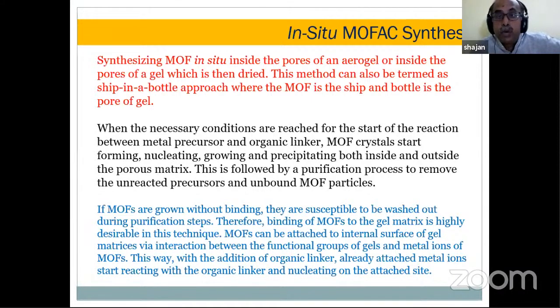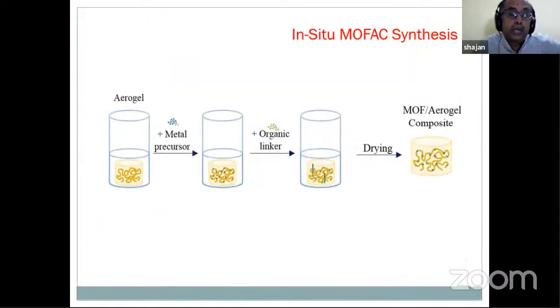The second one is the in situ MOFAC synthesis. This is also called the ship in a bottle approach, where the MOF is called the ship and the aerogel is called the bottle. Here you synthesize the aerogel, and in the pores you add the precursors for the MOF. You can see in this picture. So the aerogel is here. Now you add the metal precursors to it. Then you add the organic linker to it. Now the reaction is taking place. That is, the formation of MOF is happening inside the pores of the aerogel. Now you dry it and you form the composite.